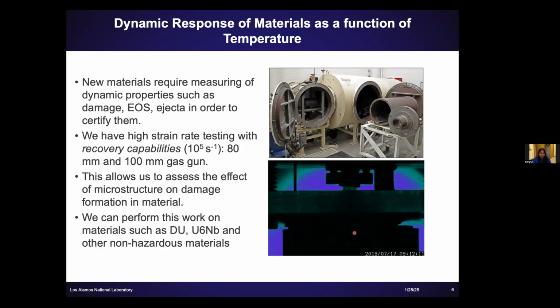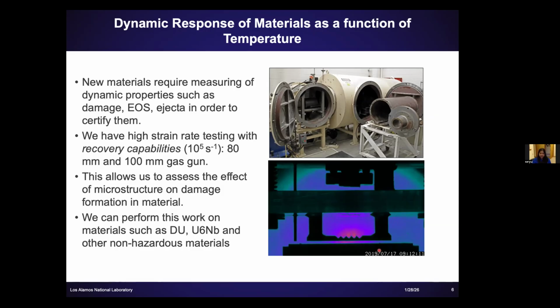We have 2 gas guns, an 80 and a 100 millimeter gas gun. What you really need to know is that it allows us to go from 50 meters per second to about 1200 meters per second in terms of velocity and pressure ranges. So when we're collecting dynamic property data, we can actually investigate a large range of pressure, which is important when you're trying to parameterize some of these properties. The cool thing about our gas gun, the unique thing, is that in addition to collecting photon Doppler velocimetry data from the back surface of the sample, we also actually recover our material.